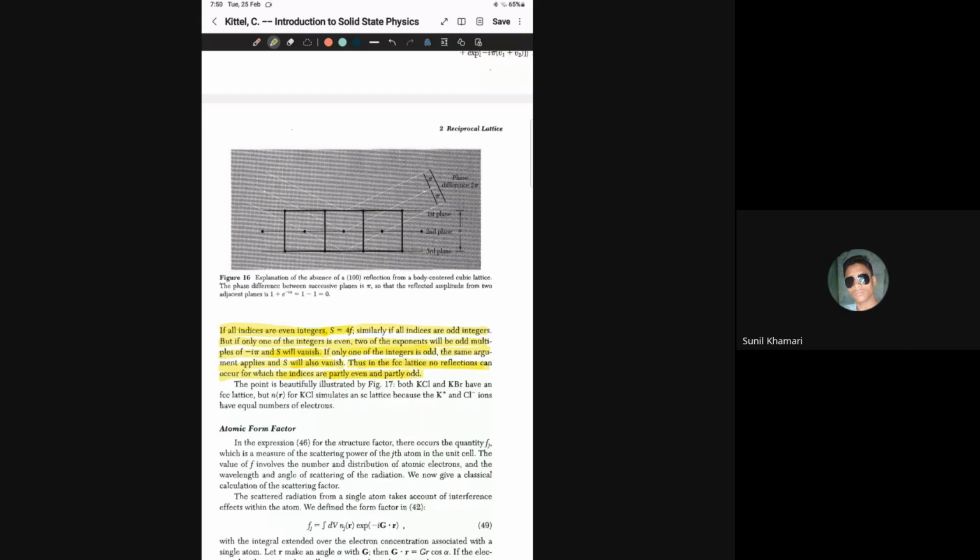So this is telling you that not from all lattice planes will we get diffraction intensities. Rather, depending on what kind of crystal we have, whether FCC, BCC, simple cubic, or base centered, we will get our X-ray diffraction patterns at different angles theta. So that is how we are getting a signature pattern from a crystal structure. Okay.